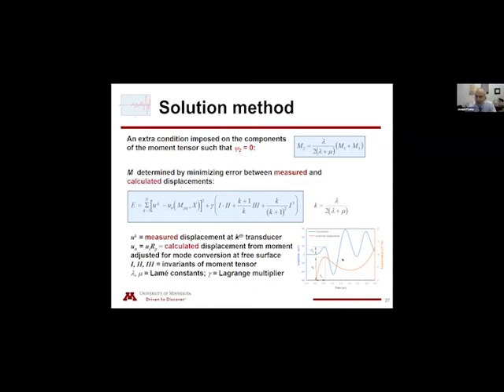I'm showing here quickly the results of a calibration experiment where we produce an artificial event, and this artificial event is a rapid unloading that's produced by breaking a glass capillary. So the blue is the signal that's measured. The orange is, if I could say, the signal that is calculated based on the elasticity solution associated with that calibration procedure. And we relate the voltage that we measure from the time history to the displacement that's calculated from this elasticity solution.